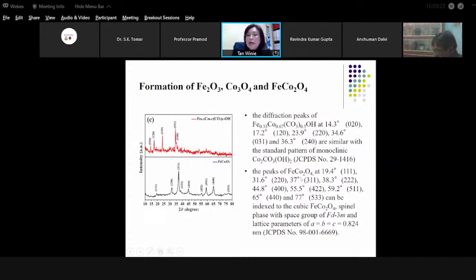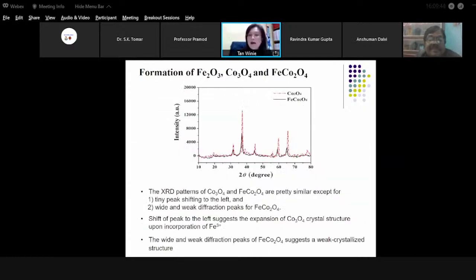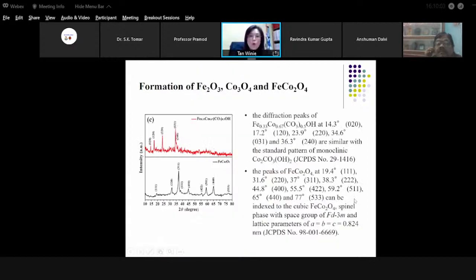And the peaks of the iron cobaltite can be indexed to the cubic spinel phase with space group Fd-3m and lattice parameters a equals b equals c equals 0.824 nanometers. So this is what I would like to share on the overlay. This is the overlay XRD pattern of cobalt oxide and iron cobaltite. This overlay XRD pattern gives us two very important pieces of information.